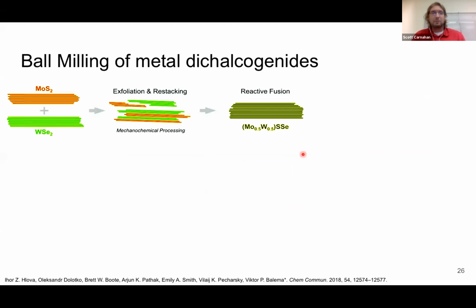One last project I'm going to talk about, which is a bit of a step sideways, is with our collaborators in Viktor Balema's group in Ames Lab. What they do is take tungsten selenide and molybdenum sulfide, which are layered 2D materials, and mix them using ball milling. The layers get interspersed, and then they do an annealing step at 1,000 degrees Celsius to fuse the sheets back together.